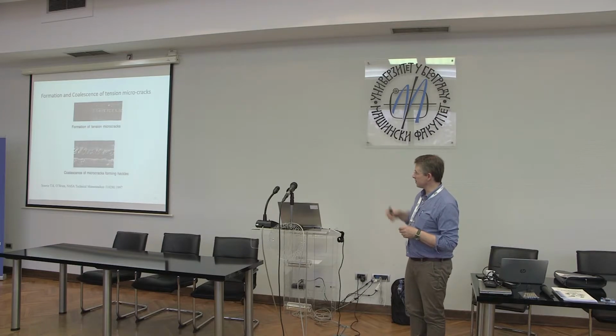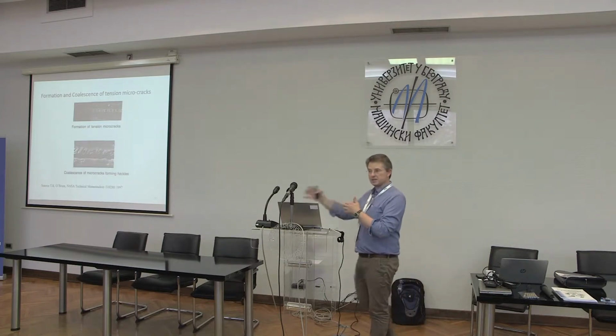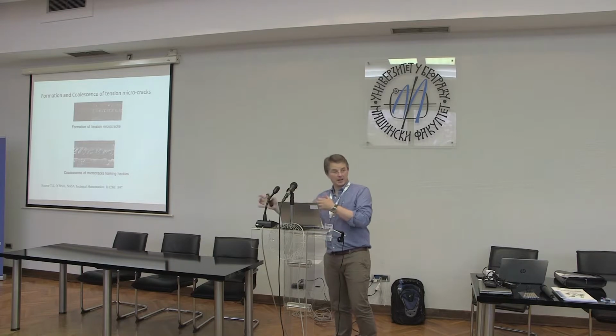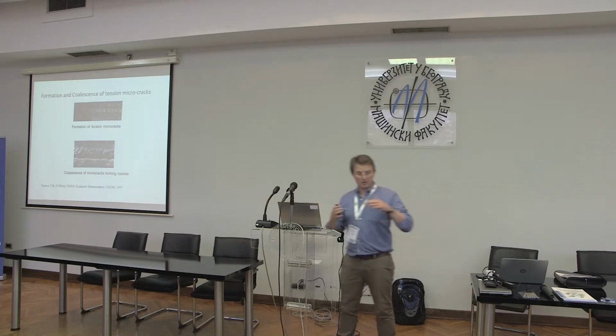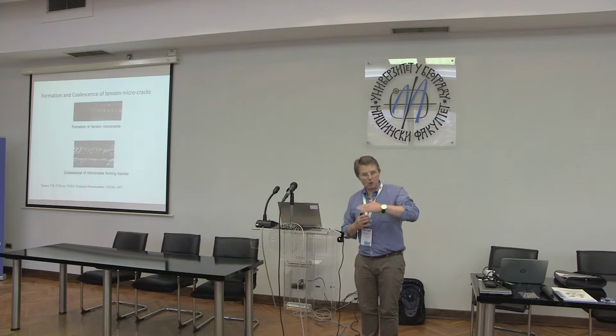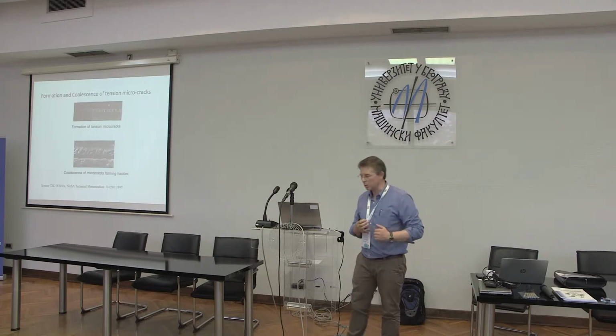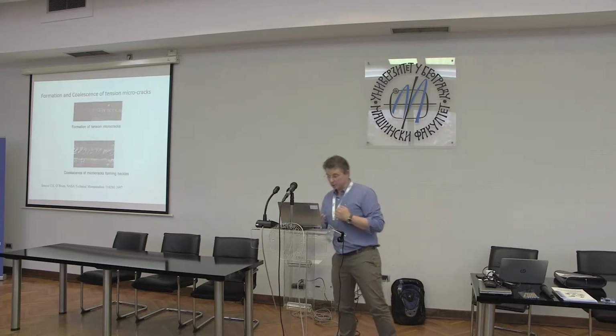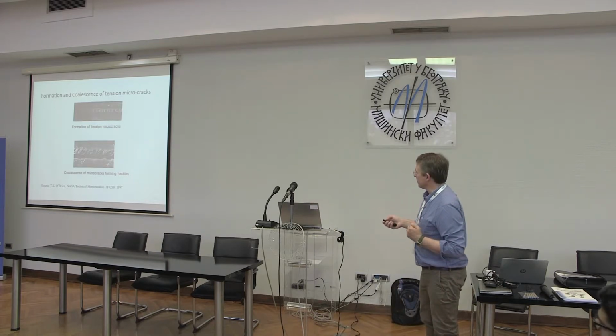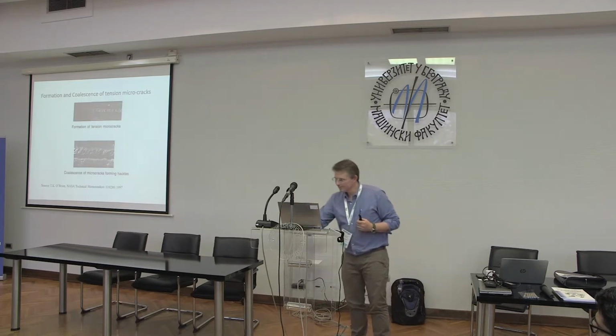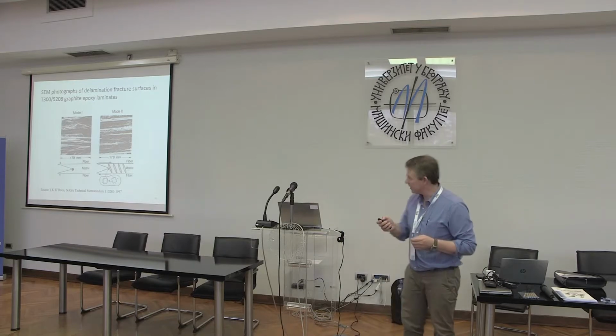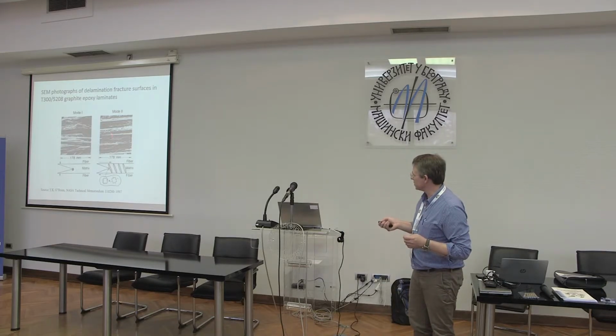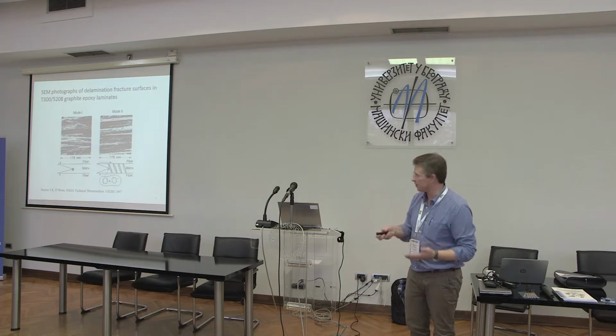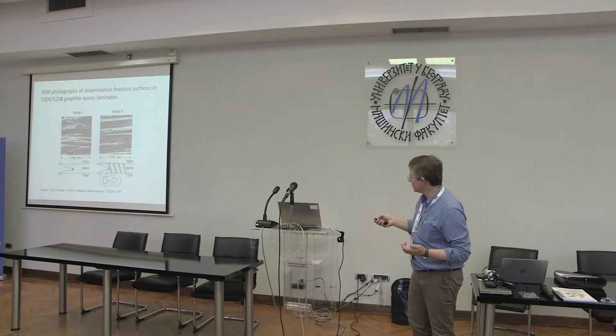So for relatively brittle materials, you get this extensive shear cracking ahead of the main crack. And what will then happen is the main crack sort of bumps along, picking up the discontinuous bits of material and shear yielding them as it goes forward. And you can see, if you just look on the next slide, what the fracture surface looks like if you actually look at the material after a mode 1 fracture and a mode 2 fracture.